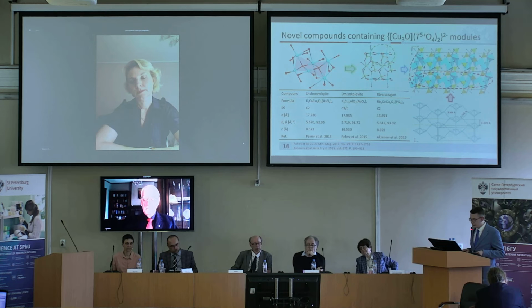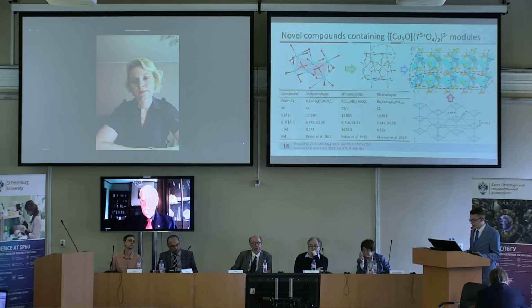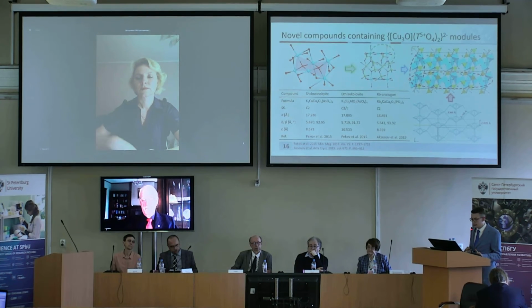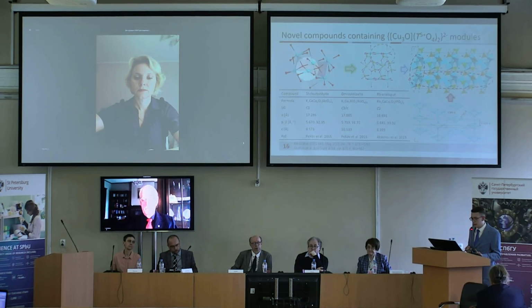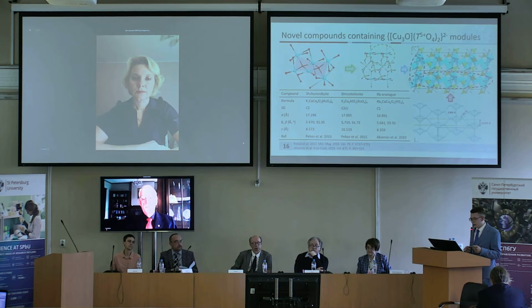In our research, we obtained 2 new compounds that can be attributed to the family of shchurovskyite. Shchurovskyite and kaliochalcite are 2 minerals, the structures of which are based on dimers of edge-bonded oxo-centered tetrahedrons. The dimers, through oxygen atoms coordinating copper atoms, are connected in chains which form layers.